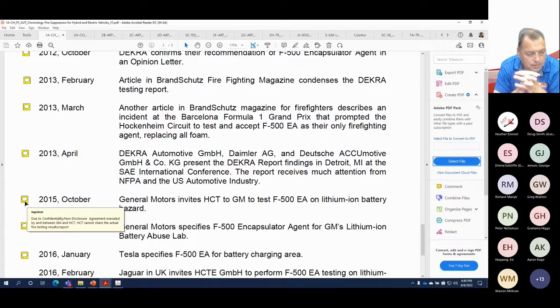We used the 20-gallon per minute TKO nozzle. And the gentleman that conducted the test is actually on our meeting here. It's one of our firefighters, Mr. Jeff Monkowski. He used a 20-gallon per minute TKO nozzle, and he had a 2-liter bottle of F500. He was flowing at 3%, and then within 1 minute, everything was extinguished and cooled. He stopped the nozzle, unscrewed the bottle of agent because the 2 liters were gone, and he screwed another bottle in while we were talking with the General Motors people and the fire protection engineer, but never had to use any of the 2nd liter. The fire was out, the temperature was down, and it never rose again.